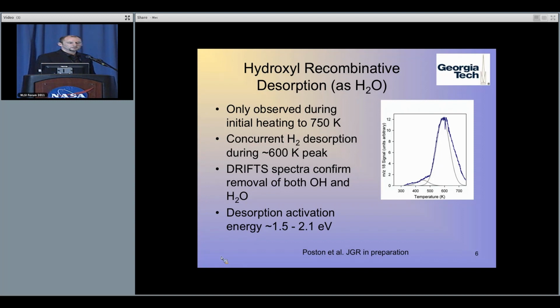We were also watching the mass 2 for the hydrogen and saw a concurrent peak with the 600 Kelvin peak. So we decided, well, this might be hydroxyls. The shape, we can't really do this experiment multiple times at different coverages to analyze the shape. So we're going to have to look at this a different way.